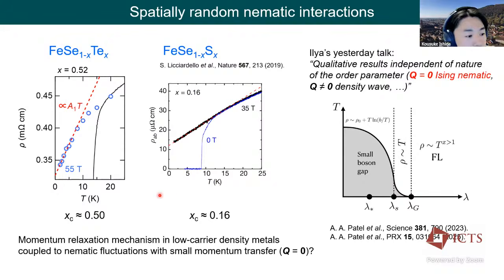And furthermore, this random interaction can provide a momentum relaxation mechanism in the metal coupled to nematic fluctuations. In iron selenium telluride the Fermi surface is very small, and the Q = 0 nematic fluctuations do not transfer large momentum, so it looks difficult to involve an umklapp process. But iron selenium telluride has a multi-band character, so there might be a way to induce an umklapp process. But again, the details would still remain open questions.